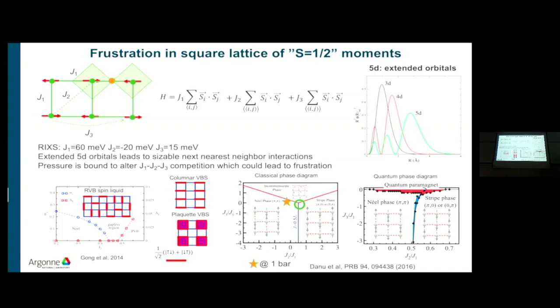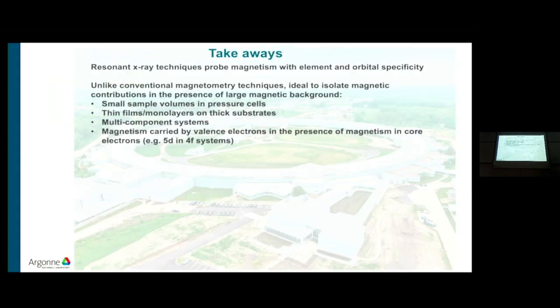Whether we have it or not, it's not clear, and the main challenge is that there is almost no technique that can probe magnetic excitations at high pressure, especially at 20 GPa or higher. So inelastic neutron scattering is very, very bad because of the collimation to look at very high pressures. And other techniques are also very hard to do in the pressure cell. So you have to look at magnetic excitations to see if the excitations are trivial, like magnons, or if it's spin liquid-like excitations like spinons, which are fractionalized excitations that are much more complex. We don't have the ability to do that, so this is something for everybody in this community to think about.